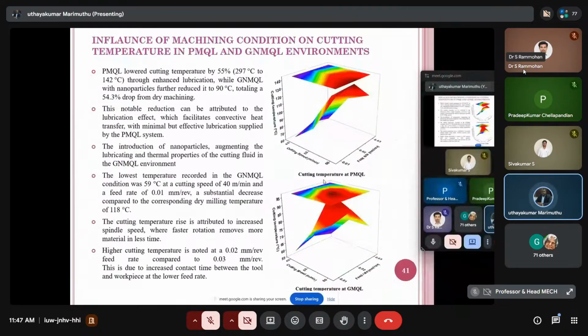Then, influence of machining conditions on cutting temperature in PMQL and GNMQL environment. Now understand the concept. Now we are introducing the coolant. In the previous case there was no coolant. Now you can see the cutting temperature is lowered by 55%, from 297 to 142. In this case it is 142. Earlier case it was 297. So approximately 55% of temperature is decreased through enhanced lubrication.